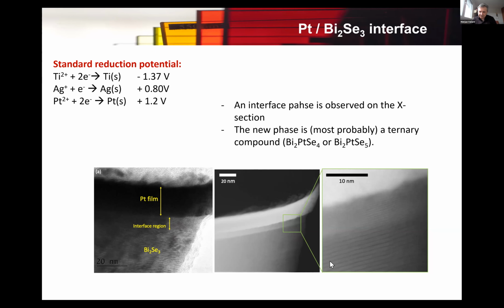And you can see typical layers of bismuth selenide, quintuple layers of bismuth selenide. But look here, you have completely different periodicity of these layers in the interface. And that means that some new compound has formed on the interface between platinum and bismuth selenide. So we still have a little bit of work to undoubtedly identify this new compound, but all the features that we have seen from the TEM research show that it can be bismuth platinum selenide, or I mean you have two possibilities, but certainly some ternary bismuth platinum selenide. So also platinum, although it's not such an intensive interaction, still interacts with bismuth selenide.